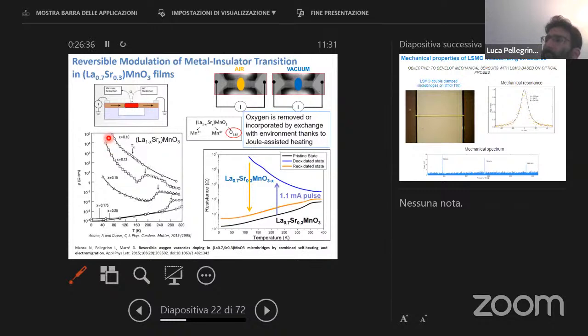So I said before, this diagram taken from this reference shows that the material has insulating behavior if you have a small amount of strontium, and you have metallic behavior if the stoichiometry is, for example, 0.25 or 0.3, and you have this magnetic phase transition, which decreases the temperature by changing the content of strontium. But you can even keep the strontium content constant and change the oxygen stoichiometry, and this can be done dynamically and in real time by changing the temperature of the system in vacuum conditions. So you place, this is the resistive behavior of lanthanum strontium manganite in this stoichiometry, and then you can apply a pulse.